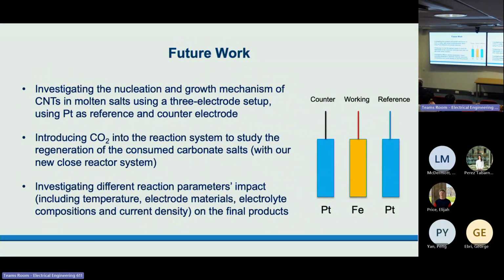So for future work, one is we want to investigate more about the nucleation and growth mechanism of the carbon nanotubes in molten salts using a 3 electrode setup. We want to introduce a platinum wire as a reference electrode to study the reaction kinetics. And then we want to introduce CO2 into the reaction system to study the regeneration of the consumed carbonate salts. But this requires us to have a closed system, not open to the air. So now we are working on that.